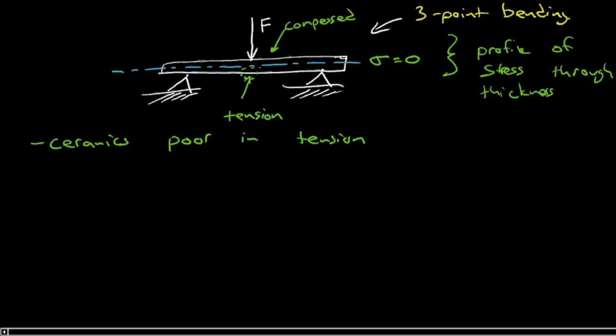In this loading configuration, the highest tensile stress will occur right here in the middle of the beam underneath where the load is applied—highest stress. The equation for that highest stress on the lower surface of the beam in three-point bending is 3 halves FL over bd squared.